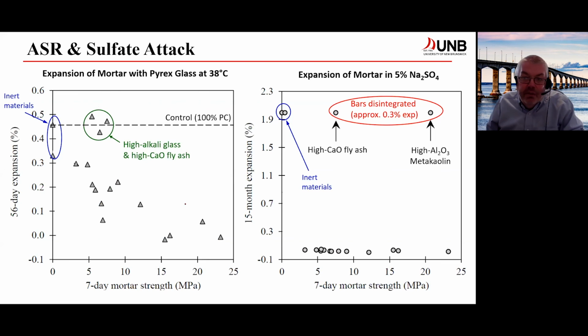If we look at ASR and sulfate attack, generally pozzolans are very good at controlling ASR and sulfate attack, but not always. That's not universally the case. Although we find that good pozzolans always reduce permeability and therefore always increase electrical resistivity, they don't always control ASR. We have, for instance, high alkali glasses that may not control ASR, even though they behave very well otherwise as a pozzolan. And then we have high alumina pozzolans, which can have very good pozzolanic reactivity like metakaolin.